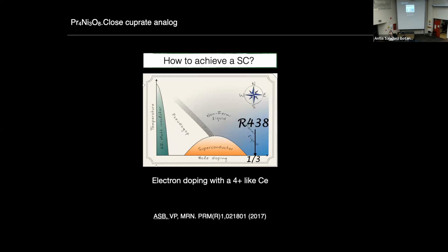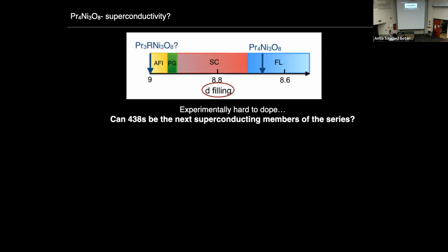So at the time we thought, okay, and you can say this is 2017, it's great that you get a metal where cuprates are metals, but nobody wants to be finding a metal, you want to be finding a superconductor. So already what we thought at the time is, well, if this material falls in the overdoped regime of the cuprates, what if I now electron dope it with a 4+ ion like cerium? And that had been done in quite a few cuprates in the past. And I'm able again to explore that side of the phase diagram. But again, you can see that that's 2017. So something must have gone off.